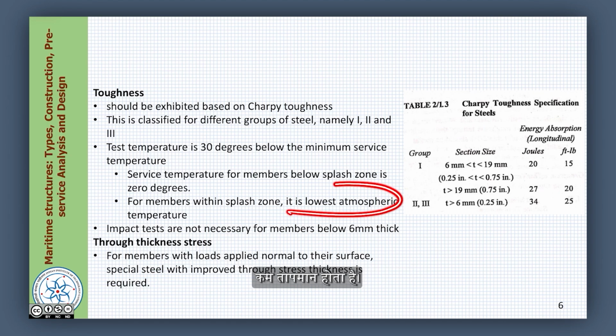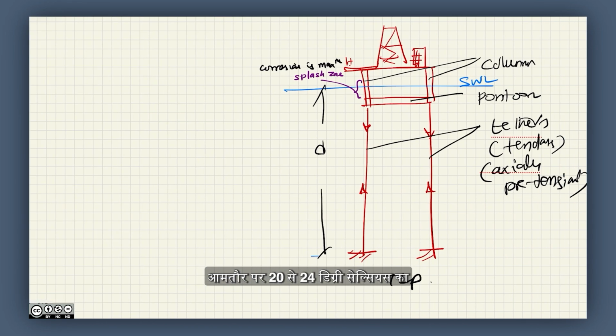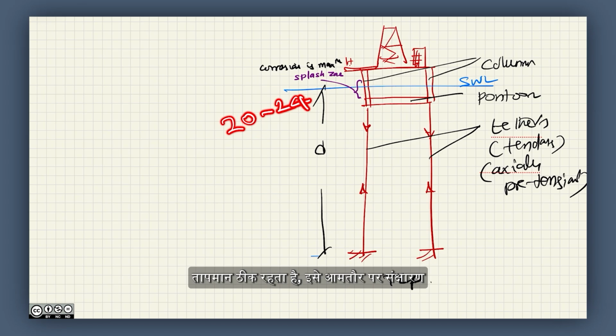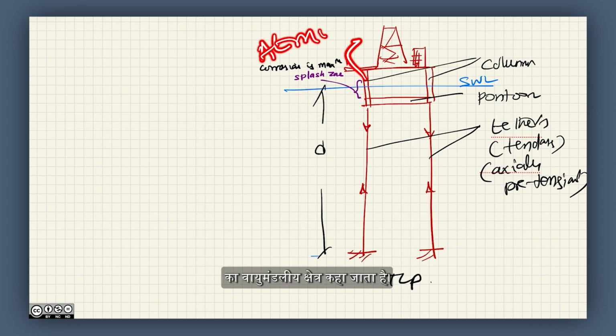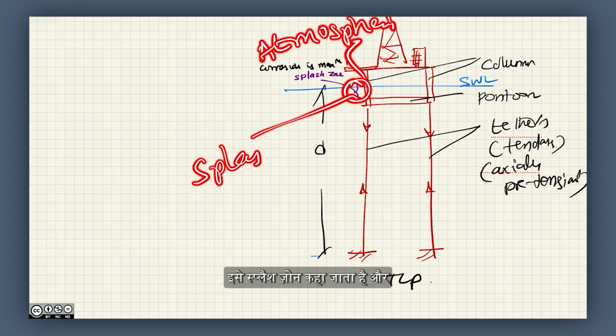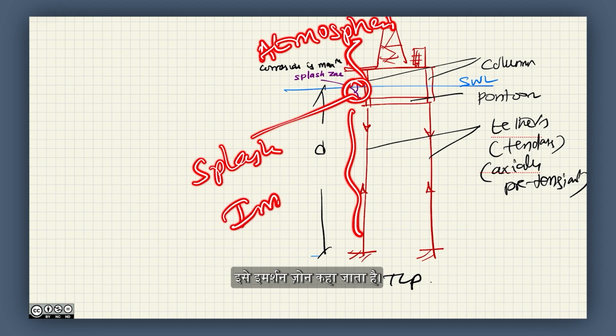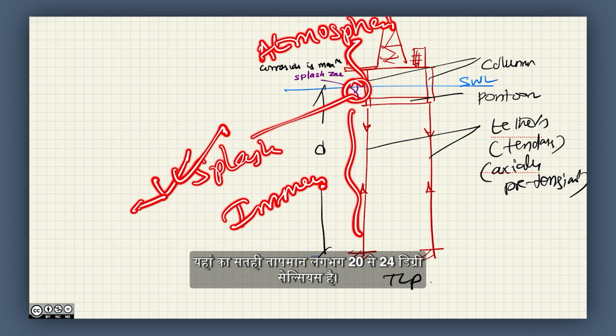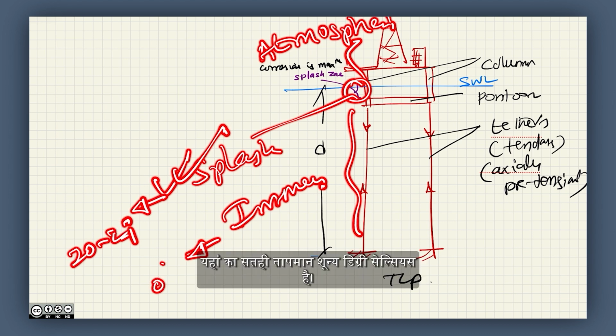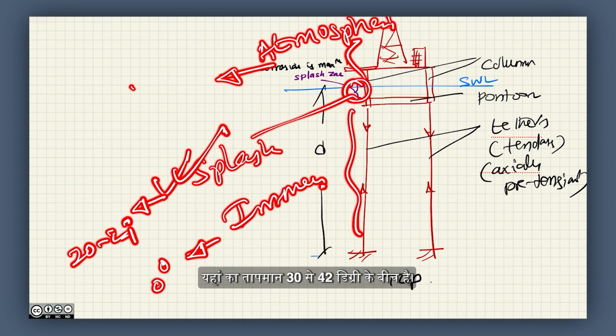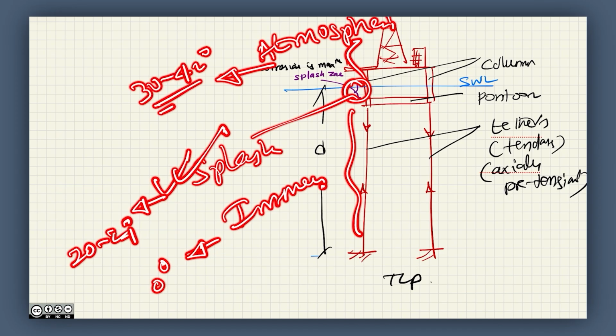For members within the splash zone, it is the lowest atmospheric temperature. Usually, it is about 20 to 24 degrees. This is called the atmospheric zone of corrosion. This is called the splash zone, and this is called the immersion zone. Corrosion is maximum here. The service temperature here is about 20 to 24 degrees. The service temperature here is 0 degrees. Of course, the temperature here is 30 to 42 degrees.